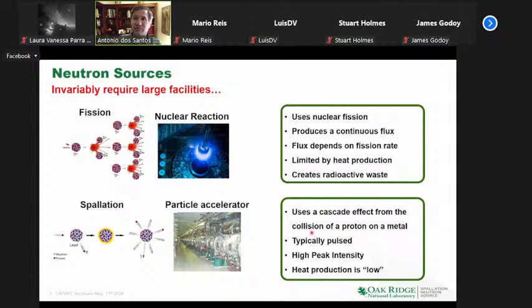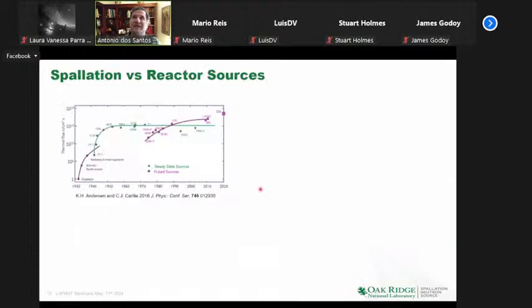So typically it's pulsed, and this is because you want a higher power to get a higher peak power, but also a higher width of neutrons, and I'll go back to that later. It has a high peak intensity, and therefore the heat production is relatively low. The corollary of that is that you can see here, this is log scale, the nuclear reactors essentially since the 60s have been fairly stable for research, while the accelerator-based sources are still growing.